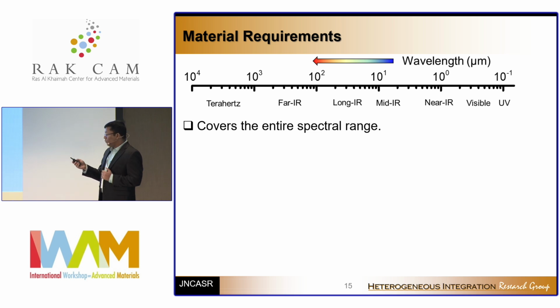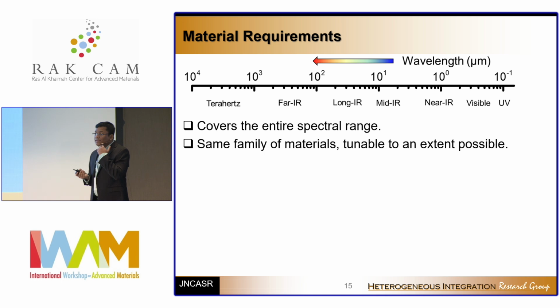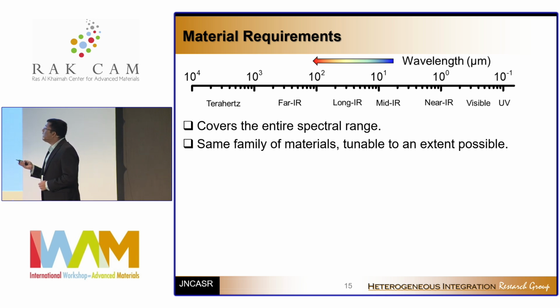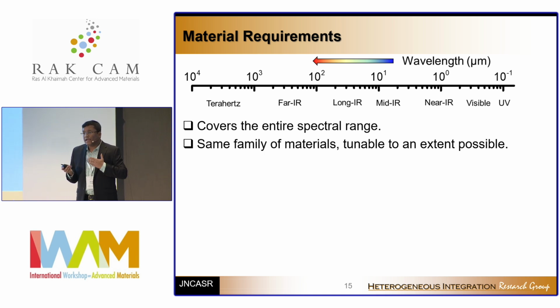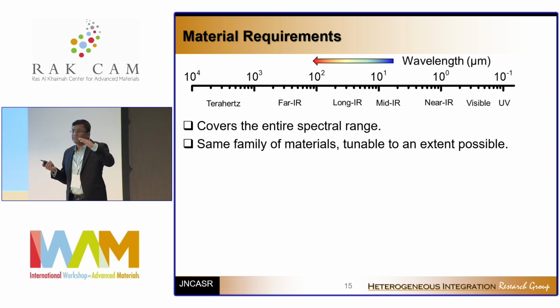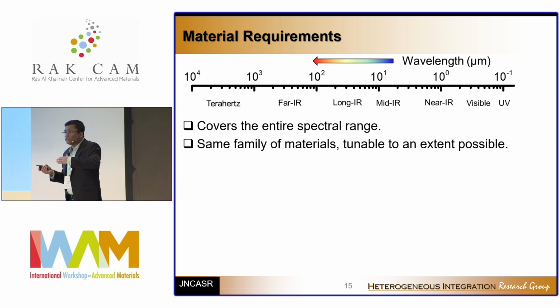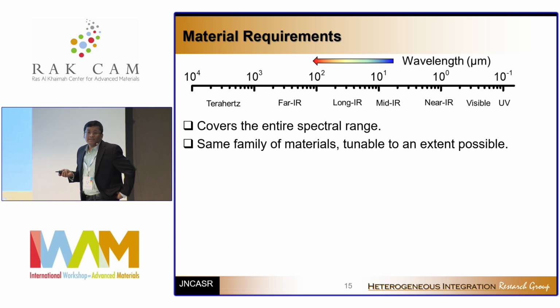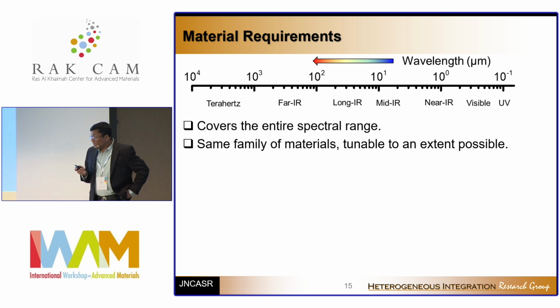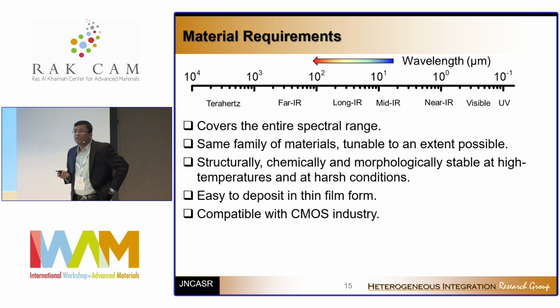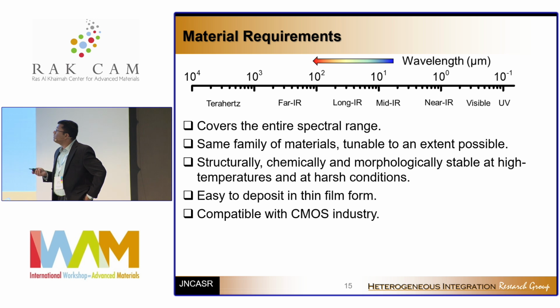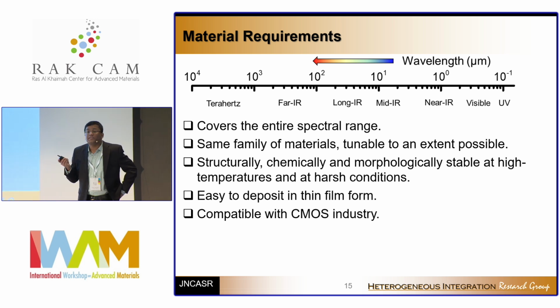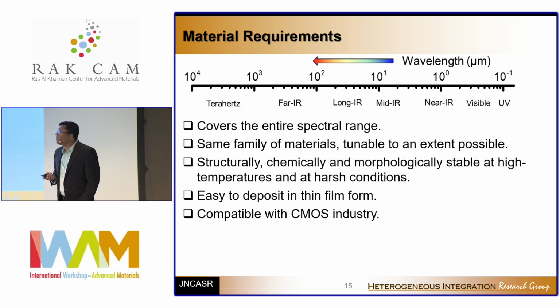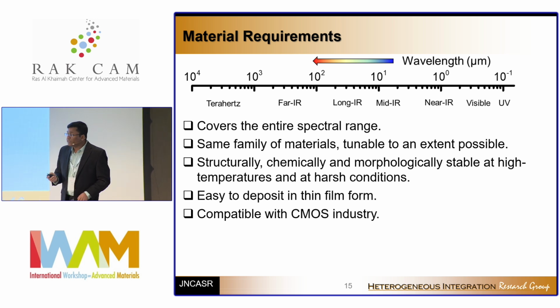So the next thing that you can do is at least find the same family of materials, either nitrides or oxides, so that you really don't have to end up growing a nitride-oxide heterostructure or nitride-sulfide heterostructure that are practically not possible. Now, if we were only doing research with it, then that would pretty much have been it. But if you really look for practical application, then along with the basic optical properties, you also have to be careful that the materials you're working with are stable, they are compatible with the existing CMOS technology, and at least you can deposit them in the thin film phase.